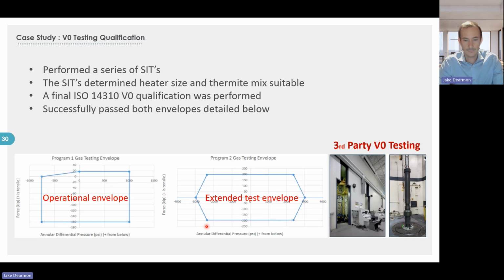So, for this particular PRT development project, we went through a full testing campaign, which culminated in a final SIT with a third-party V0 test here, and that's what we see at the bottom, or the actual envelopes here, with 3,000 PSI of gas pressure, 200,000 pounds of compression tensile loading during that testing. So after this SIT, we actually got ready to go to the field.